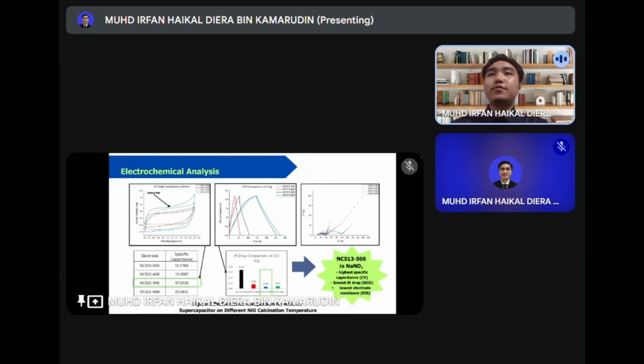Now, moving on to the result of our study of electrochemical analysis. We synthesized NiO and AC composite and tested it using PVDF, PTFE, and our proposed Tapioca Starch. From our analysis, we found that NiO calcined at 500 degrees Celsius, labeled as NCS13-500, gave the most optimal performance. It showed the highest specific capacitance, the lowest IR drop, and also the smallest semicircle in EIS, which means lower internal resistance and better ion transport.